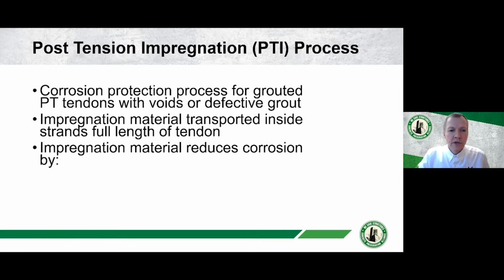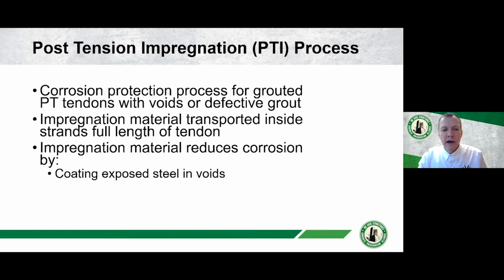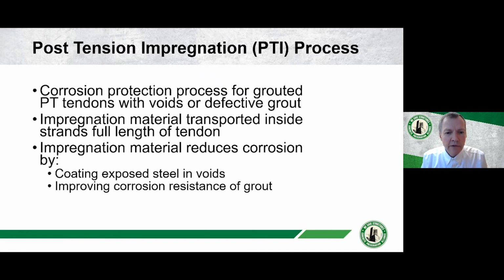The impregnation material reduces corrosion by two mechanisms. The first is that in locations where you have voids and you have exposed steel, the material will form a coating or a film on the exposed steel surfaces. And so obviously that means exposed steel in voids, but it also includes the internal surfaces of the strands themselves, where corrosion can also be an issue. And the second mechanism is that the material soaks into the grout surrounding the tendon or the strand, and by doing so it improves the corrosion resistance of the grout. It increases the resistivity of the grout, and it also makes the grout more hydrophobic, or repels water, and effectively keeps water away from the strands.